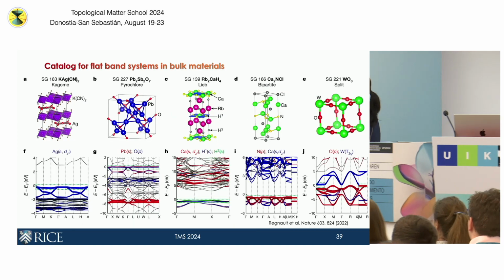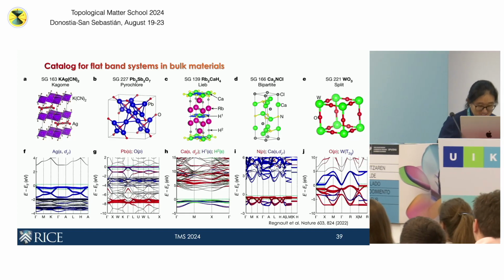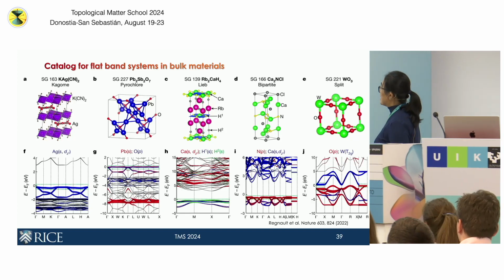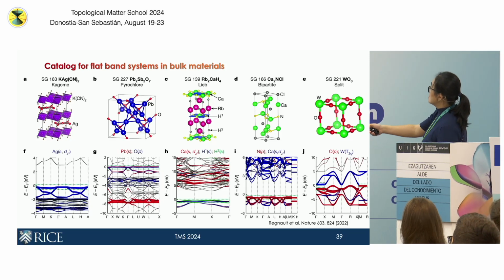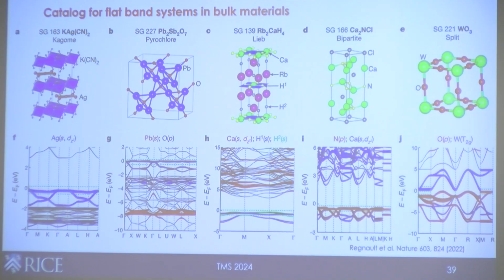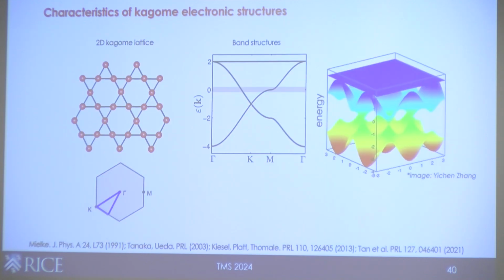Okay, so here we go. Since Stephen has already given a complete introduction of this, this is easier on my part. He talked about the Kagome lattice, and of course, he also mentioned that in the materials that we have, there's actually a vast number of such lattices that can give you flat bands. So this is a very nice catalog work that shows some of the common ones, like Kagome lattice, pyrochlore lattice, Lieb lattice, bipartite and split, and so on and so forth. And in real materials, you can actually see DFT calculations showing flat bands near the Fermi level. Okay, so cool. So this is what we wanted to study, and I'm going to tell you about 3 such systems that we have looked into.